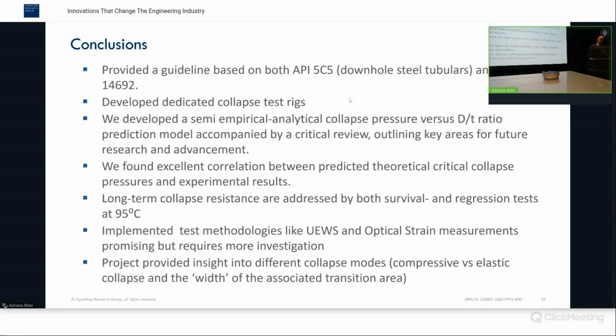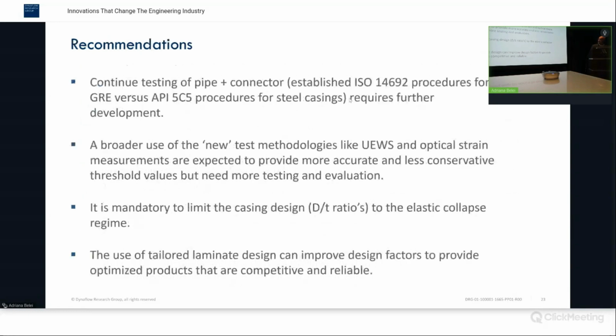Implemented test methodologies like UEWS and the optical strain measurements are promising, at least for certain composite designs, but this requires more investigation. The project provided much insight into different collapse modes, compressive versus elastic collapse, and the width of the associated transition area. Then the recommendations: the project intends to continue testing of pipe connectors. That has not yet been implemented. We developed the guideline to do the testing, but it needs to be demonstrated that it is successful in the future.